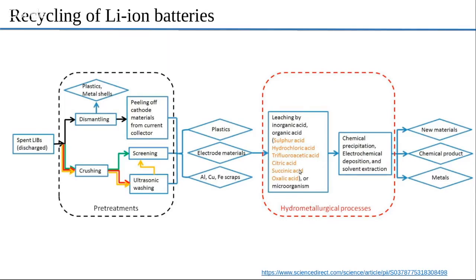You pick the kind of acid that will dissolve only the material you want. It won't touch, affect the other materials. So you pick the kind of acid that is good for, let's say, aluminum or copper or cobalt or nickel. Then you leach that away. And then you have a slurry or an acid which contains dissolved nickel or cobalt aluminum.